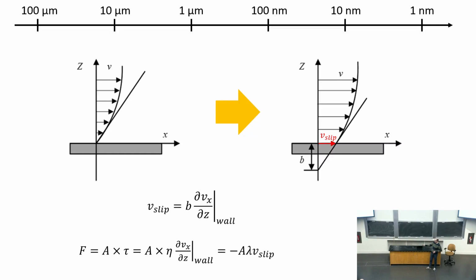And the viscous stress can be written as the viscosity times the velocity gradient here. And in a general case, if you just assume a linear relation to the slip, then you can write this in this way, where lambda is the friction coefficient. Taking these two together, you can see that the slip length here is suggested to be just a ratio between the viscosity and a molecular coefficient that defines friction at the wall.